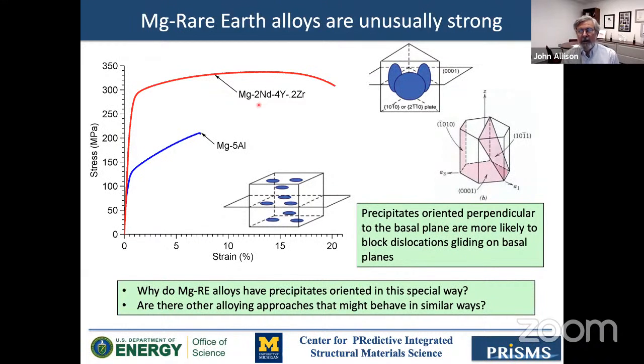As I said, magnesium alloys can use a little bit higher strength, a little bit higher fatigue strength, et cetera. So we knew that the magnesium rare earth alloys have much higher strength than the conventional alloy systems that we're used to. We also know why that is, and it's because these are precipitation hardened alloys, and the precipitates in these materials are orthogonal to the basal axis. So the primary slip system in many magnesium alloys is the basal slip system. So you'd like to interfere with slip on that system. And so having precipitates that are perpendicular to that slip system is important.